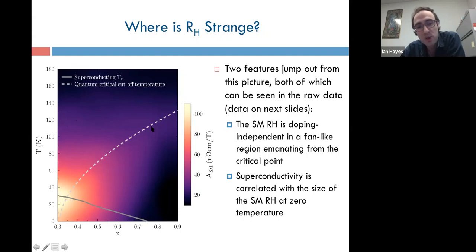The first is that if you look at high temperatures, the strange metal part of the Hall effect is independent of doping. Throughout the very broad region of doping space, you simply get the same field dependence for all your samples. As you decrease the temperature, the window over which that is true decreases. And it decreases continuously and seems to vanish near 30%. And thereby traces out the kind of fan region that you would often draw when describing quantum critical systems with a single tuning parameter. So this looks very much like there's some detuning energy in the system that is getting stronger as we move towards higher phosphorus doping, such that if temperature is larger than that detuning energy, you simply get the same effect, independent of what your actual doping value is.